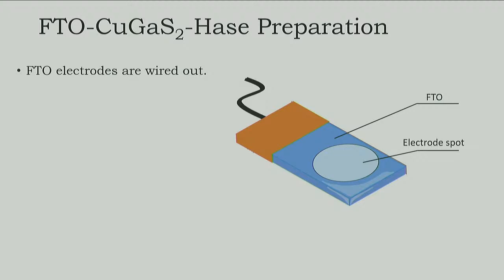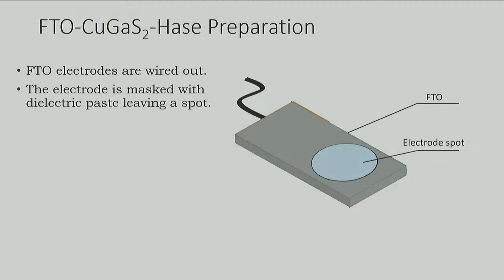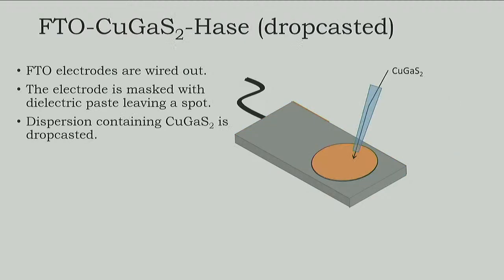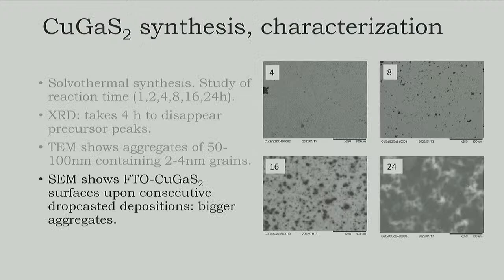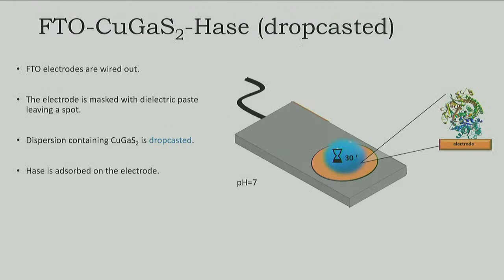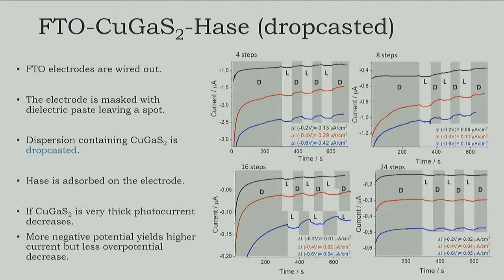Okay, so we tested different kinds of immobilization techniques. I'm going to go a little bit fast through this because most results are really hard. We tried different ways to modify the electrode. First, by drop casting, after different cycles of drop casting, we put the ternary sulfide here. We immobilized the enzyme just by letting it adsorb, which for hydrogenase works much better than for laccase. And this is the kind of response we were getting here. Okay, so when we illuminate, we get this tiny photoresponse, which to us is not very high.